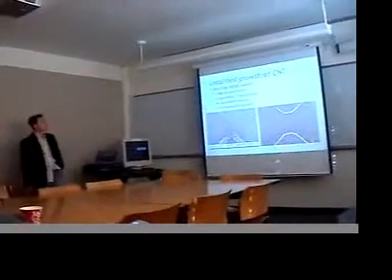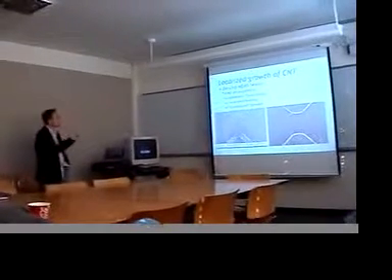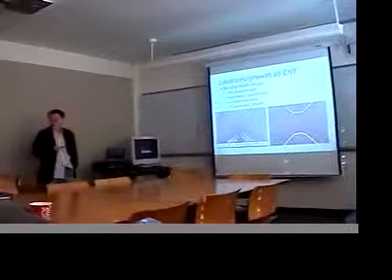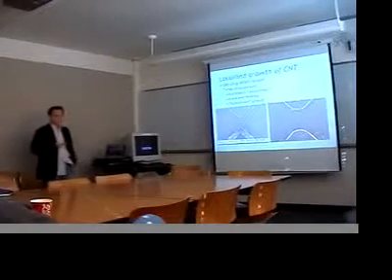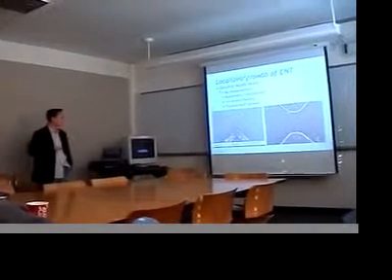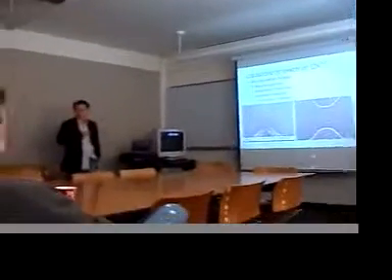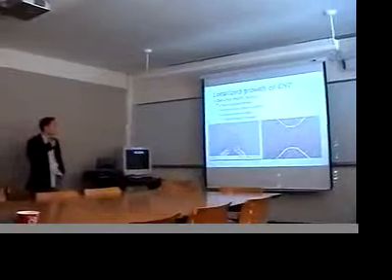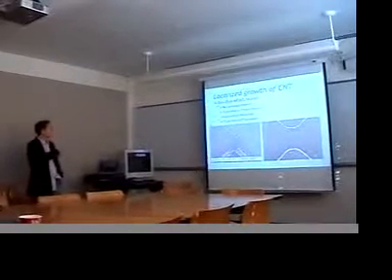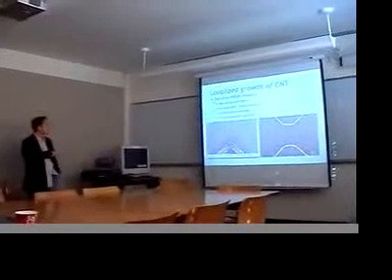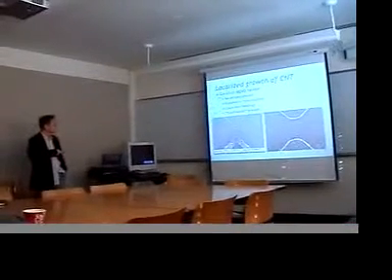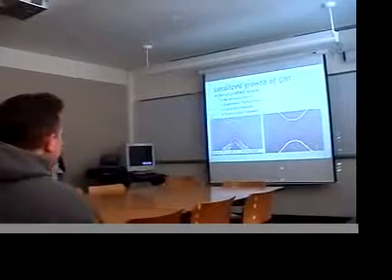So what our group proposed is a localized growth of CNT. In my opinion, it's just a variant of CVD. So instead of subjecting the whole sample to very high temperature in a furnace, we provide a heat source with a MEMS heater. I'd like to give credit to our PhD student who has left us already, Dane Christensen. His idea is to use the MEMS heater to provide a heat source, and we evaporate the catalyst on top of the heater, and sure enough, you can see the carbon nanotubes growing up.